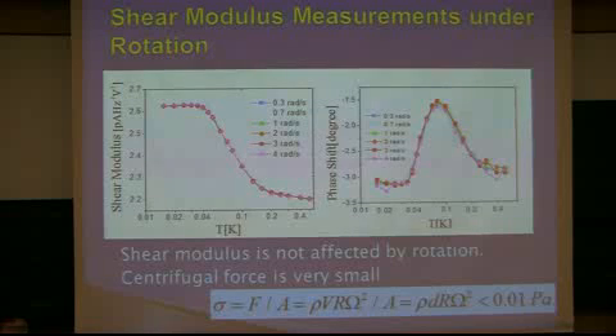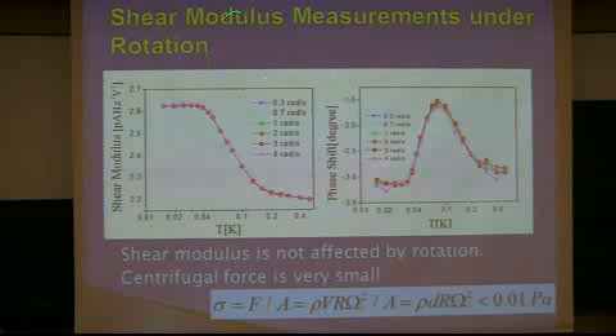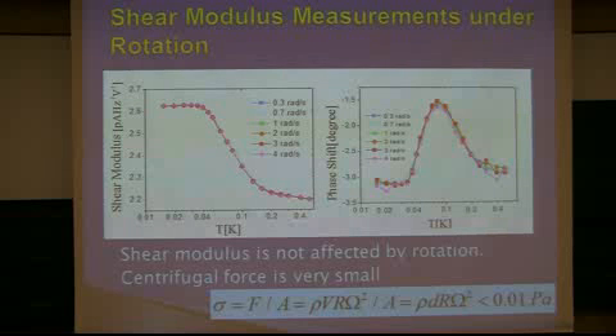So what happened to the shear modulus? Let's start talking about the experimental results for the shear modulus. As I told you, we don't expect any change in the elastic modulus because we just change the frame from rest to rotation, and the rotation speed is sufficiently small. And this is the result. Shear modulus as a function of temperature, and this is the phase shift, which is proportional to the energy dissipation, as a function of temperature. We have 4 different rotation speeds and measured the shear modulus. There is no change, as we expected, right?